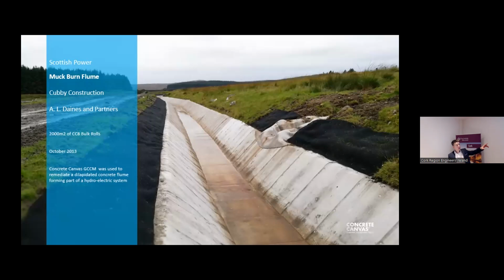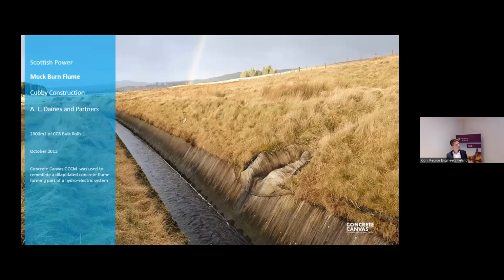There's also a number of inlet channels it needed to accommodate on the right-hand side, just to bring some water in from that slope. And they installed some erosion control matting on both sides of the channel, just to ensure quick germination on both sides of the channel. This was a photograph from 10 years later. So as I mentioned earlier on in the presentation, the GCCM material will blend in a little bit better with the surrounding landscape over time. And that's primarily due to the hydrophilic top surface, which has a buildup of algae and moss over time. So you can see that finished project after 10 years.